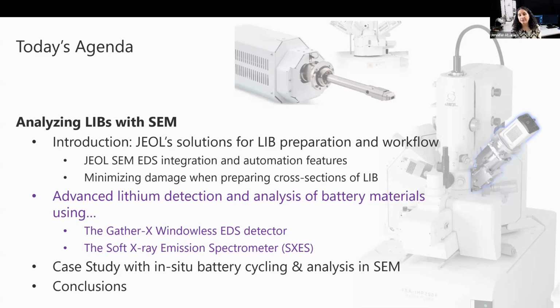And I will address how to minimize sample damage during preparation with a focus on JEOL's cross-section polisher, a critical tool for preparing lithium-ion battery cross-sections for high-resolution imaging and analysis. The core of the presentation will explore a collection of data taken on various battery materials, especially focusing on lithium detection in different alloys and compounds using two of JEOL's state-of-the-art X-ray detectors on our ultra-high-resolution SEM platforms, the Gather-X Windowless EDS detector and the Soft X-ray Emission Spectrometer.